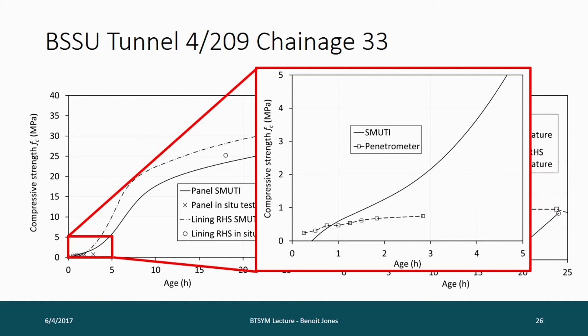But the penetrometer, when you accelerate concrete, the accelerators we use are mostly aluminium sulfate, and that reacts with aluminates in the cement and creates ettringite. And the ettringite crystals consume a large amount of water. There's something, I think it's 32 H2O in every molecule of ettringite. So it basically creates a massive drying out of the concrete. So what you've got actually is a very well compacted and low slump concrete that you're trying to push a needle into.